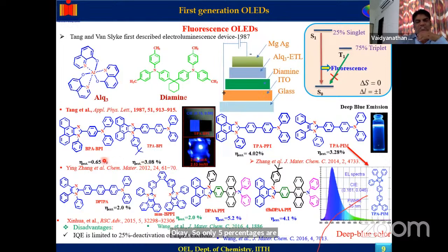So the limitation of this external quantum efficiency is very clear. For example, here the triphenylamine is directly connected to the imidazole ring, and you get an efficiency of 0.65%. The moment you put one phenyl ring, or benzene ring, in between this donor and acceptor, the external quantum efficiency improves drastically from 0.65 to 3.08. So there are many cases where one can use device architecture or design strategy to get a deep blue emission.